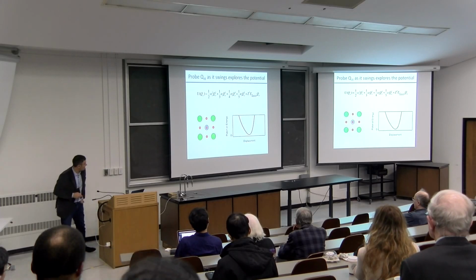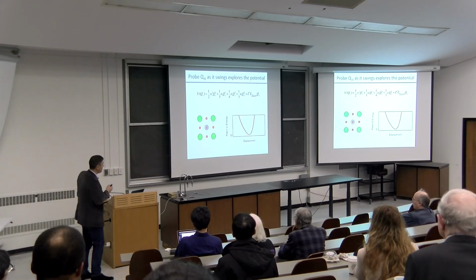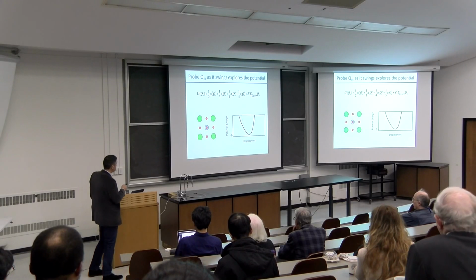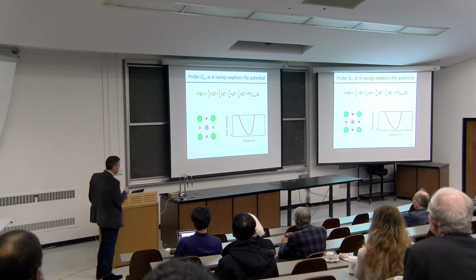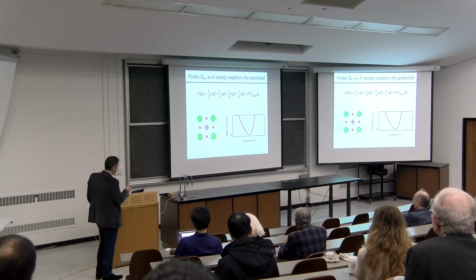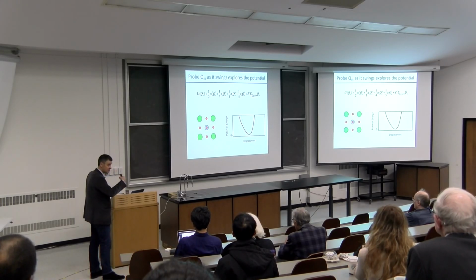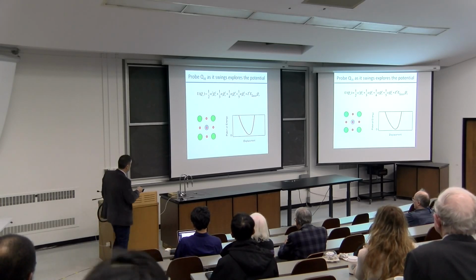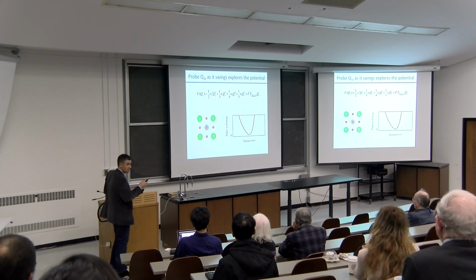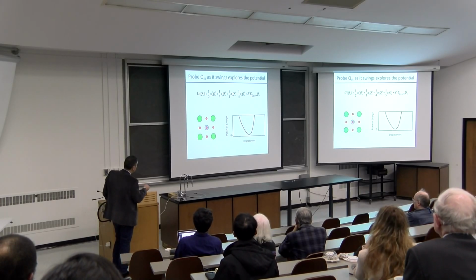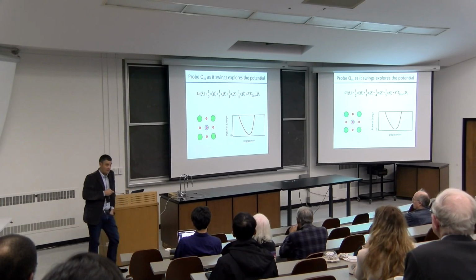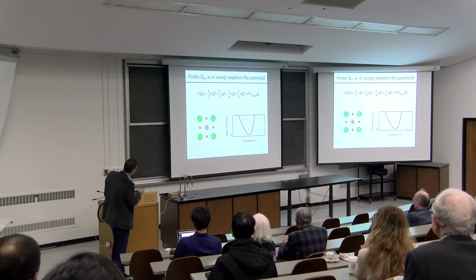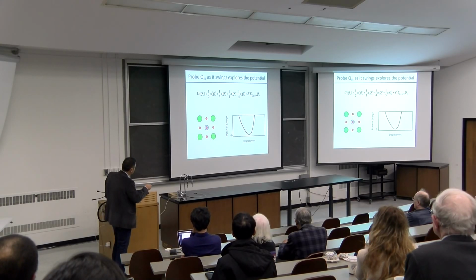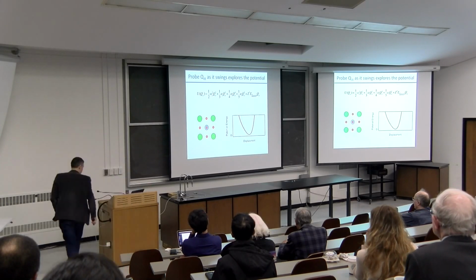So basically, if you take lithium niobate and you drive Q_IR to large enough amplitudes, what you're going to get is an energy potential that now depends only on Q_IR. As I said, I switched off the coupling to all the other modes. This system breaks inversion because it's in the ferroelectric state. So you will have both even and odd expansion terms of my potential. So my energy, as I told you before, is going to be all sorts of terms of expansion plus the contribution that I gave you before from the laser and the coupling.